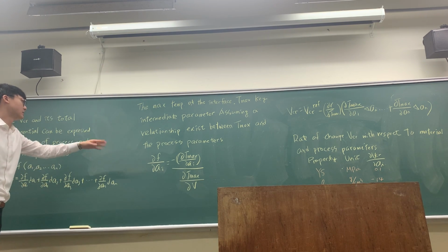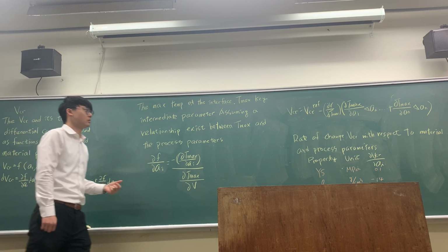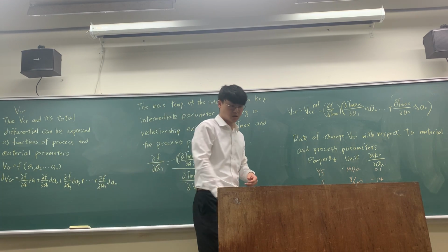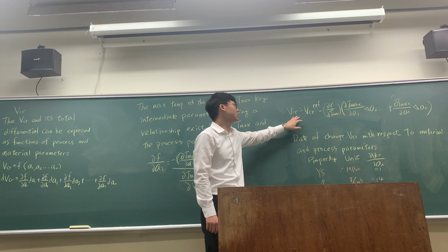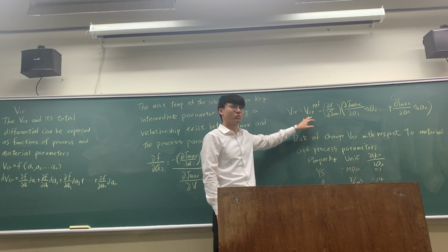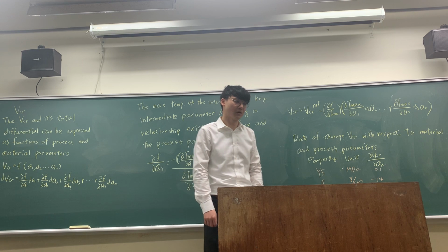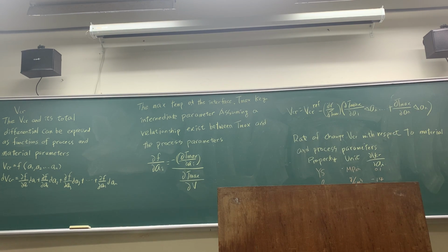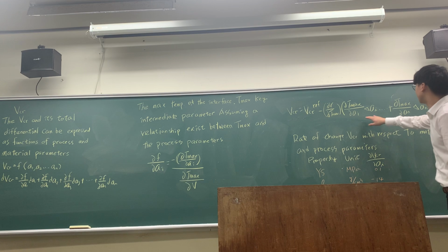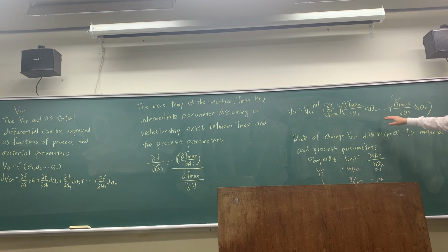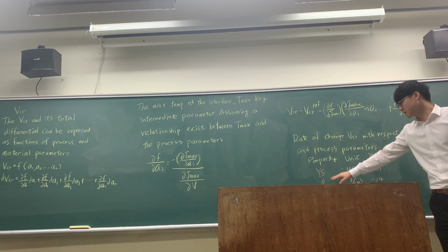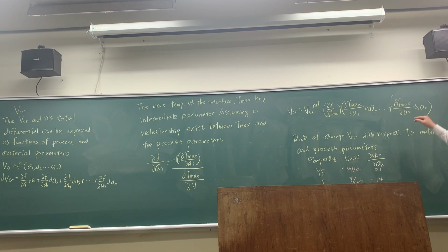So if you bring this equation back over here and do your partial derivation, you get VCR equals VCR reference. The reference is, today, this author has used copper as its reference particle, so I believe it's 600-ish meters per second. Minus over here, these are all the material parameters, depending on what A1, A2, A3 are. I only listed a few: the yield strength, density, and modulus that fit into these functions.